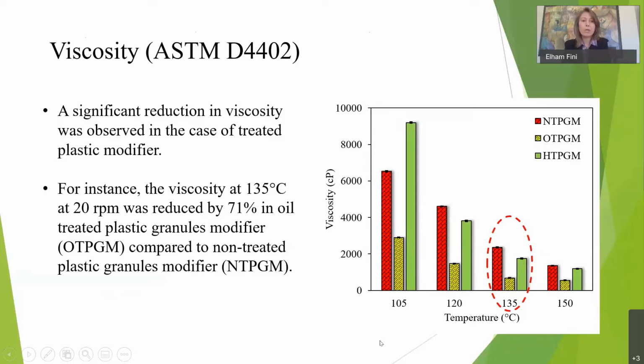one test here. So the test is run at 20 RPM. We apply shear and we apply torque and measure the resistance to shear. So the resistance to shear is then converted to calculate the viscosity value for each material.